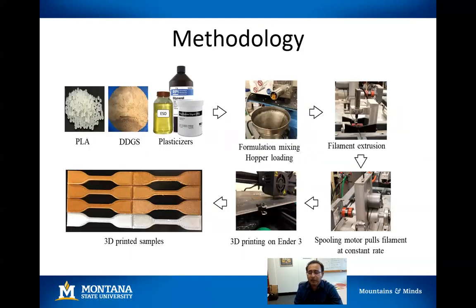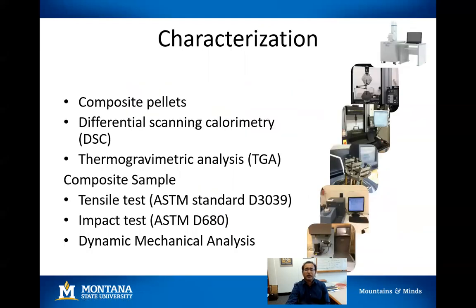So the sample preparation methodology included basically taking the materials, blending them together in a container manually, and then dropping them into a hopper of a twin screw extruder. So we used a twin screw extruder to blend the material. This is how a filament is coming out of the extruder, and then it is wound on a roller or a spool, and then this spool was used on a 3D printer to print different objects, as well as the 3D printed samples for testing. The characterization of composites was done on both pellets as well as the composite samples. We ran several tests using DMA, a universal testing machine, and also we used the DSC and electron microscope, as well as an impact tester.